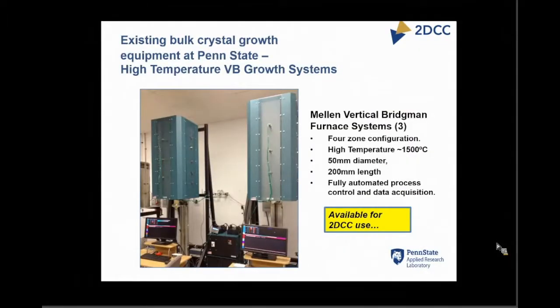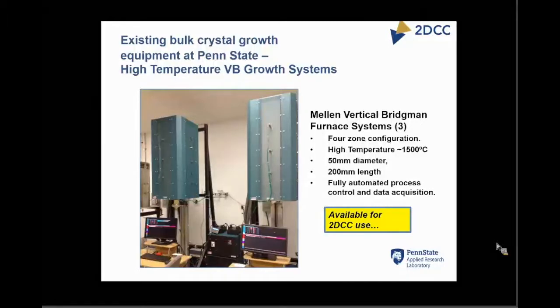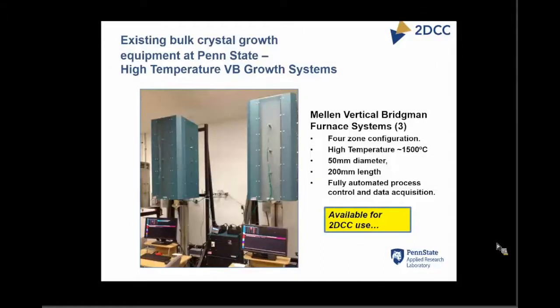Beyond that system, there's a variety of other crystal growth capabilities here at Penn State. I have a laboratory in Innovation Park and in Freeport, Pennsylvania, with a variety of systems that are being made available on a limited basis for crystal growth programs in support of the 2DCC. So this slide just shows some of the other systems in my lab. We've got 3 of these new vertical Bridgman systems that are slightly larger, 4-zone configuration. And a key feature here is we got higher temperature capability. So if someone really needs to look at a material with a melting point above 1250, these systems could be used for that.